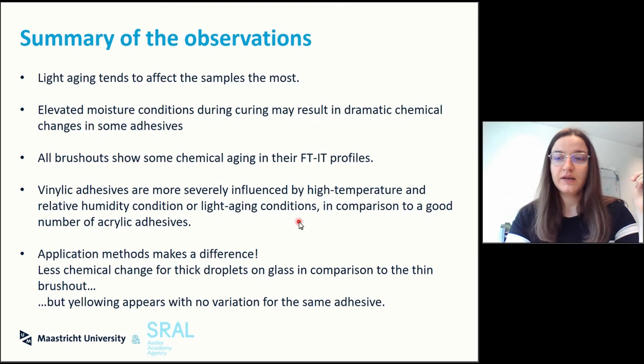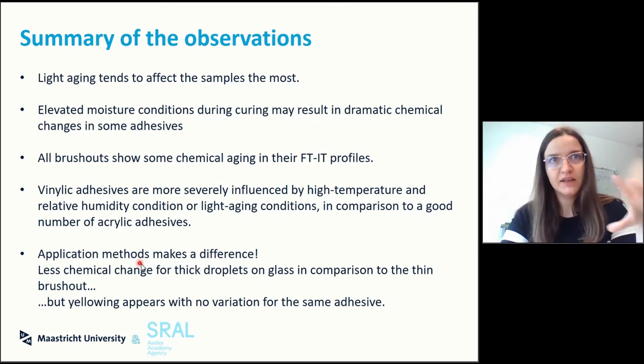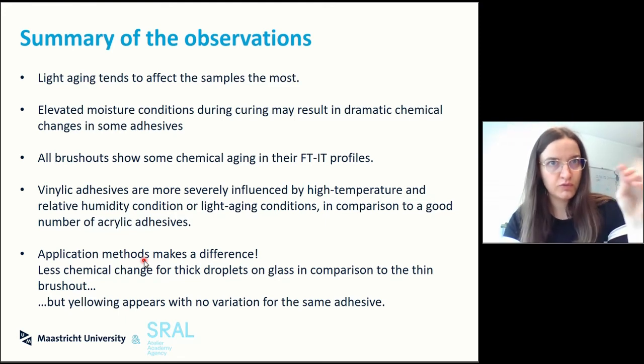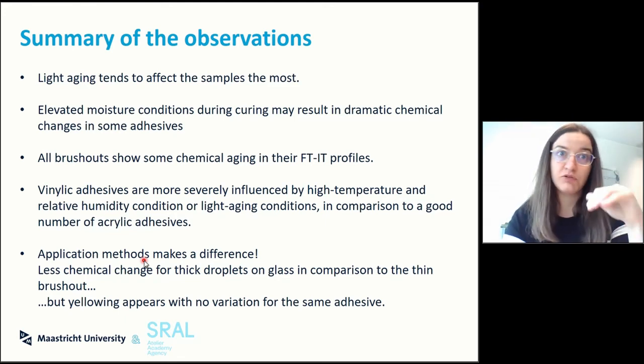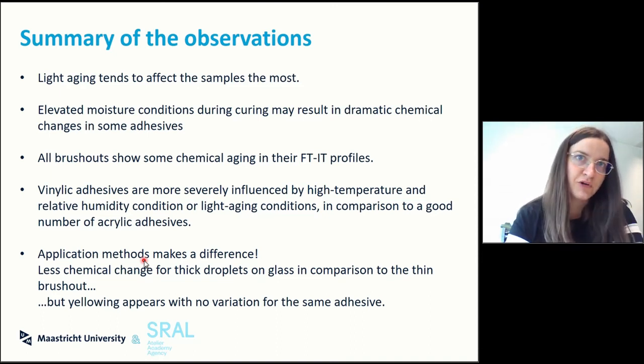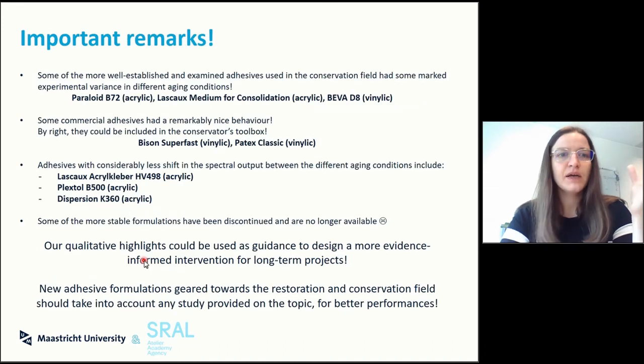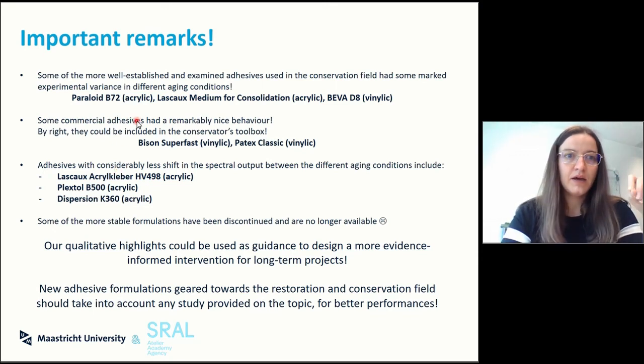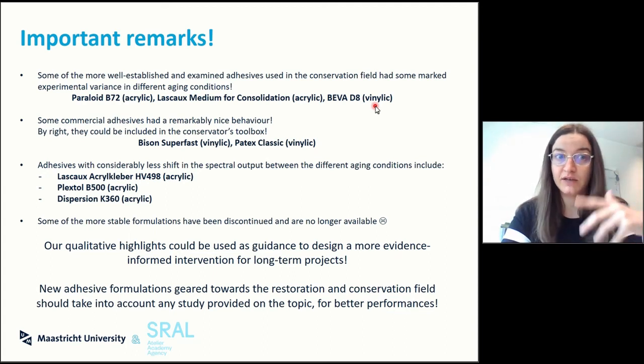Some important remarks that come from this study, which is overall qualitative, and we're not trying to do something quantitative bond by bond, because we cannot do that not knowing the full formula of proprietary adhesives, are that there are some well-established and well-examined adhesives that we tested in this study that show a real experimental variance depending on how you age them. So it is worth checking out the conditions of the aging, because these adhesives that you might think are very well established, incredibly reported in the field, might actually surprise you at the end.